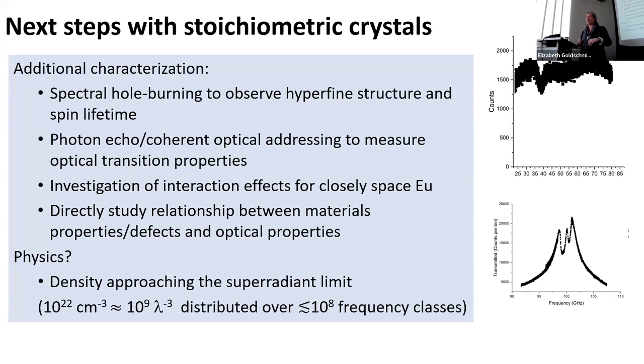I mean, those peaks that you have might be a signature already of some collective interactions. I don't think they're collective. I don't think that's what that is. Not sure, though. We're really not sure. It's weird that those peaks are polarization dependent. At some polarizations, we see one peak, and at some we see two, and at some we see three, and the orientation of our crystal is also random, and so different crystals show different structures. We're not really sure what's going on here, so we're trying to figure that out.